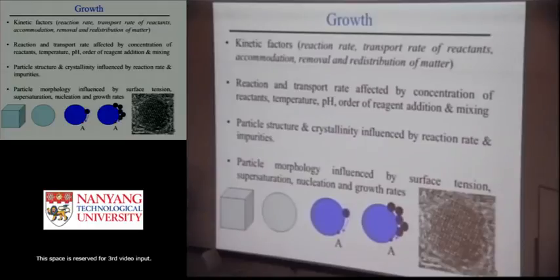They can be related to the crystal structure of the nanoparticle. In some cases you make iron oxide, Fe3O4, and if you make it relatively bigger, let's say 100 nanometers, you can actually see a lot of cubic shaped nanoparticles generated rather than spherical. That's because the surface energy in this case is not so high and does not play a critical role. But if the surface tension is high, in many cases you will see the particle is spherical.